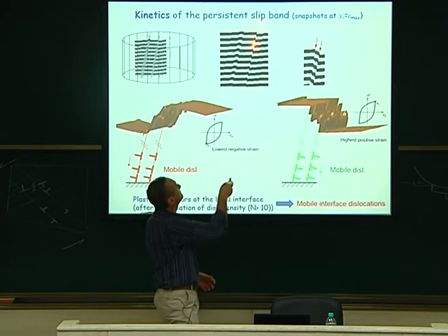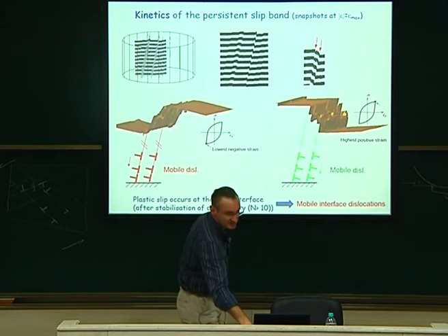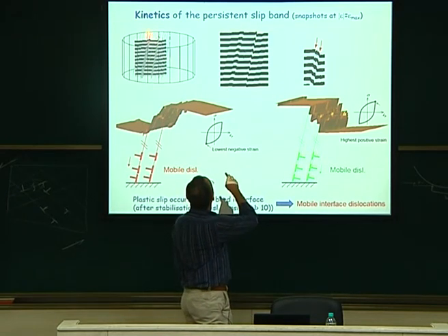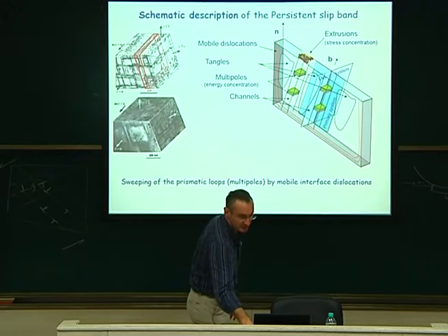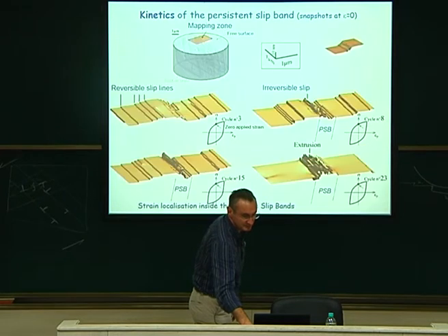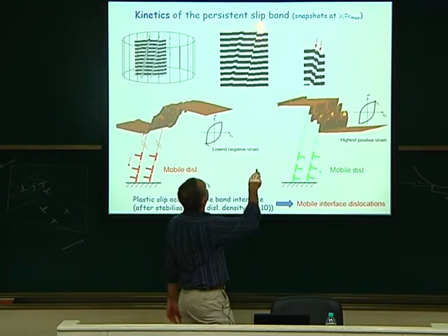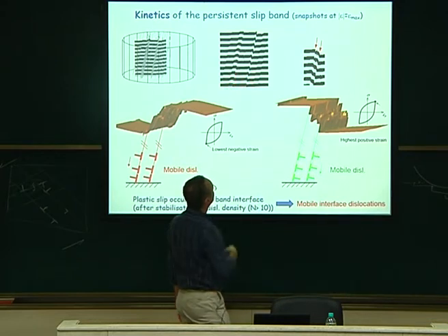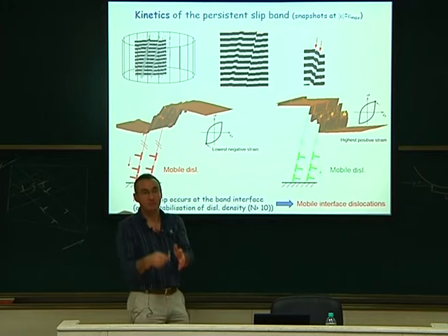You can see that this is the band, and you can see that the plasticity is occurring at 2 sides of the band, there and there. You can see that you have plastic strain located, okay, at this is the band here. The plasticity is just localized here and there. This is another band here. Plasticity is there and there. Okay, it's not inside the band, but you have shear.